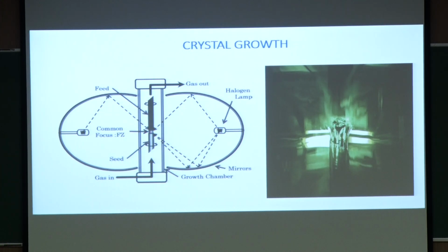So basically, what you're doing is converging all the light that is emanating from this lamp into this very small volume. The size of this volume will, of course, be determined by the size of the filament that you're using here. If you use a point source, you get a point over here. But of course, you cannot have a point-like filament, right? So the filament has a certain size, and in fact, you need a certain size because you would want the heat flux to converge over a small volume, not too big, not too small, just the size of this crystal that you are trying to grow.